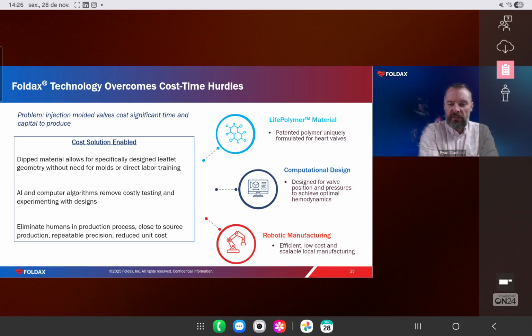So we've got a couple of mantras here at Foldax, I would say 3 of them, that are focused on reducing costs, both for cost of manufacturing, but ultimately cost for patients and payers. Injection molded valves cost a significant amount of time and capital to produce, even if you are using an injection molded polymer. And so we use a dip casting method. It allows for the leaflet geometry to be formed without a mold and no direct labor, training that with automation. And the computer algorithms that we use in computational design can remove a lot of testing and experiments that you do through design iteration.